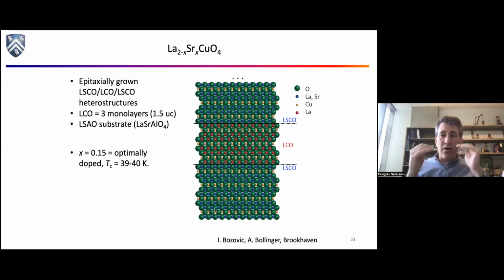So they can grow with atomic precision. They've spent 20 plus years figuring out how to do this. So this is not a trivial thing, but they can grow atomically precise layers of lanthanum strontium copper oxide, right? So you're sticking some strontium in here. That's the thing that's giving you charge carriers. That's the thing that's making this stuff conductive. And what they've done is they've grown a layer of LSCO, and then they've grown a few layers, like 3 layers, 1.5 unit cells, of the undoped stuff, the parent compound, pure lanthanum copper oxide. That's the insulator. That's the exotic insulator.